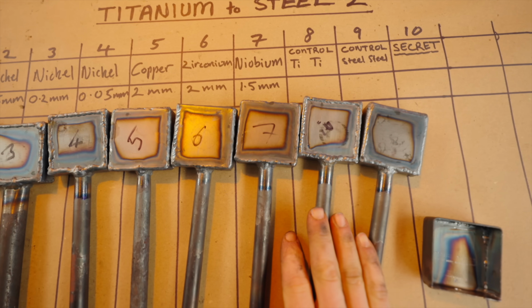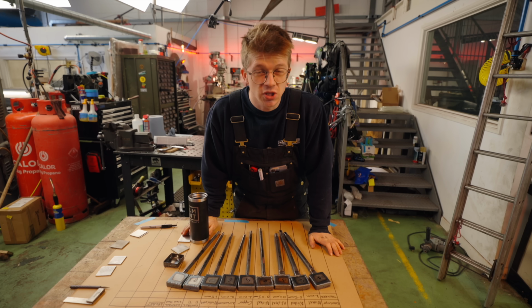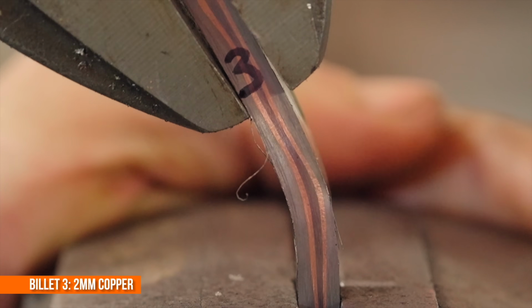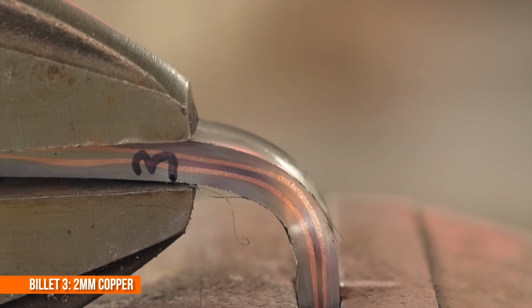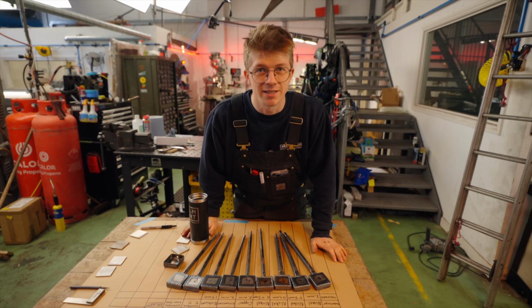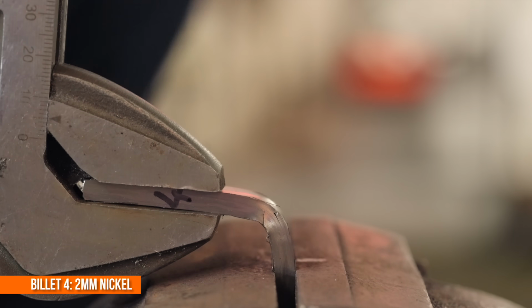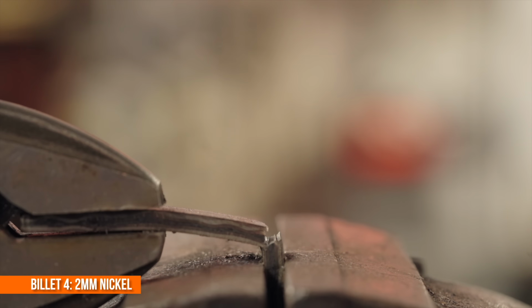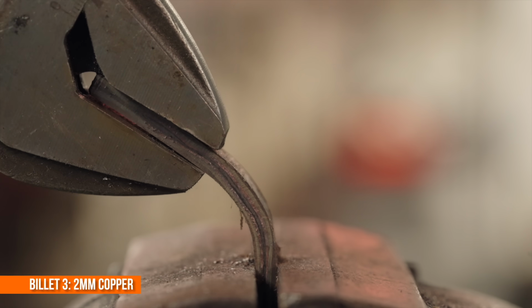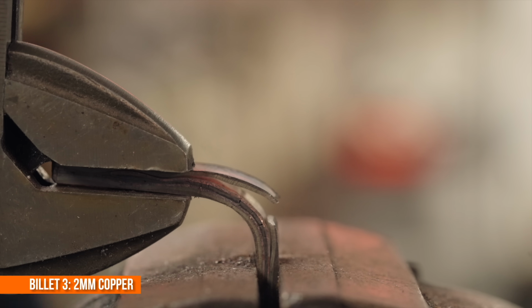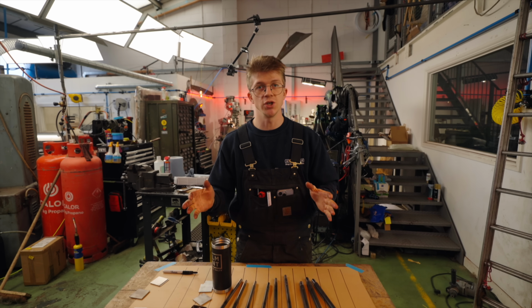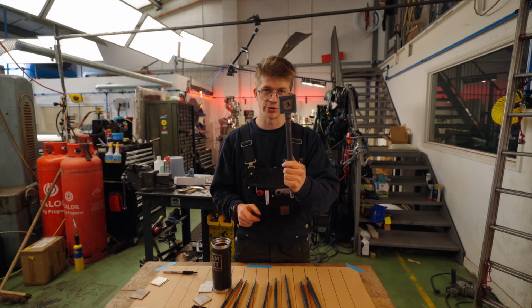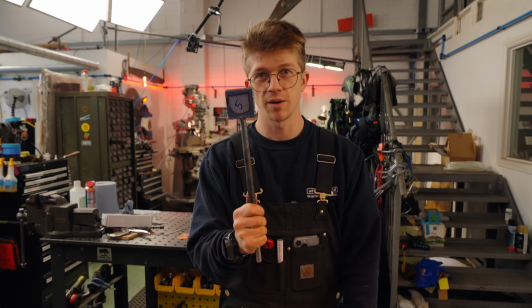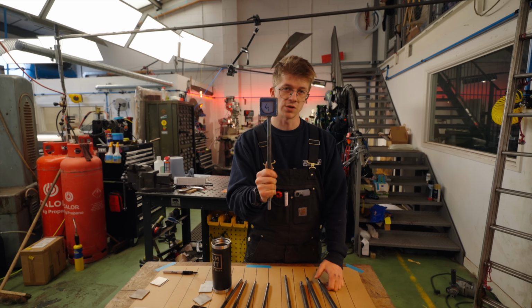I've got 9 billets ready to go, and let me tell you why we went with these materials and thicknesses. In the last episode, I thought the winning interlayer was the 2mm copper. However, you guys in the comments spotted something that I didn't. Our 2mm nickel samples fractured with a lot less delamination than any of our copper samples when they fractured. And so we're continuing our experimentation with nickel with a wider range of thicknesses, as well as our original 2mm. Of course, we've still got a sample of 2mm copper, what I thought was the winner from last time.